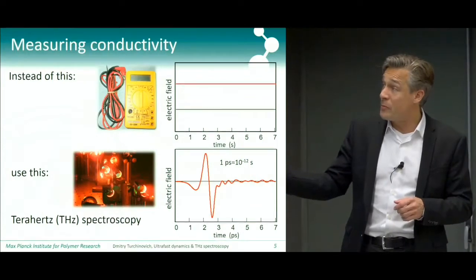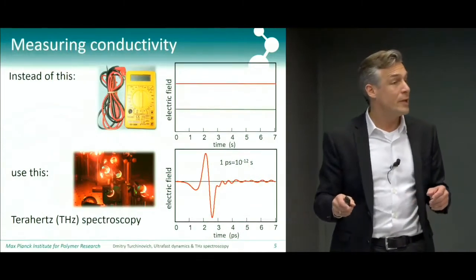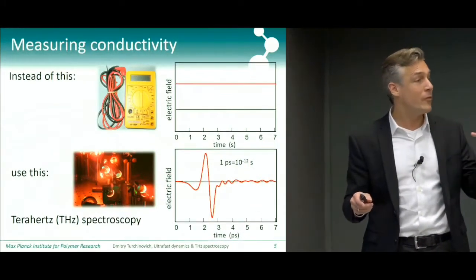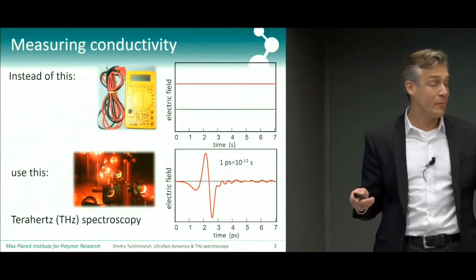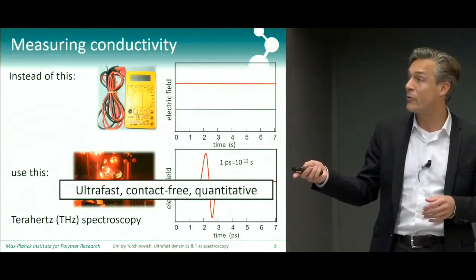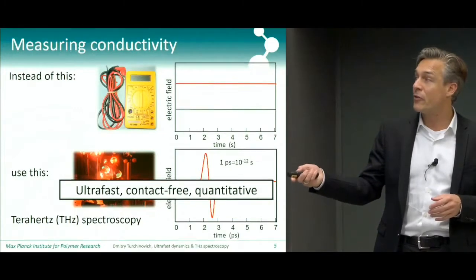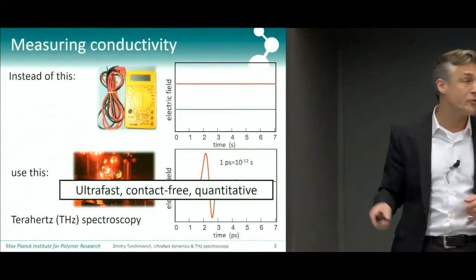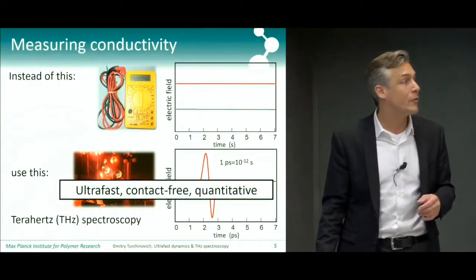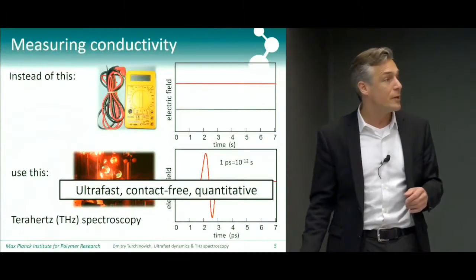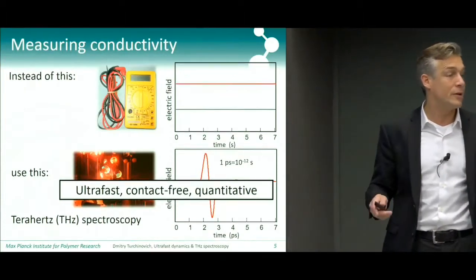The other thing, of course, is because this pulse is very short, it means that we can have very high time resolution of about a picosecond, which is also useful. So this technique is ultrafast, contact free, and I'll show you it's a quantitative way of measuring conductivity in any material, and in this case in graphene.